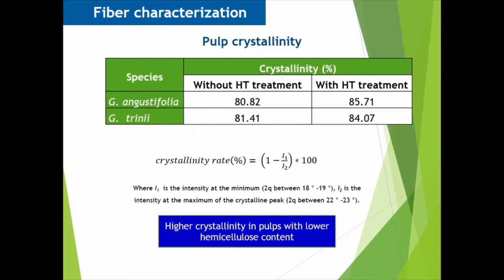The crystallinity of the pulp was obtained using X-ray diffraction equipment, and the crystallinity was calculated with the equation shown. The crystallinity in both species was higher than 80% and higher in pulps with hydrothermal pretreatment. This result can be attributed to the lower amount of hemicellulose present in these pulps, which have an amorphous structure.